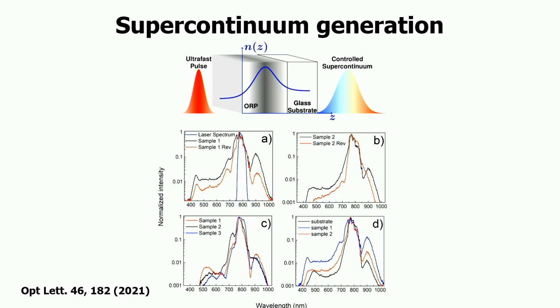So in these structures, we showed that we indeed have broadband negative GVD, and as a consequence, we can use them for enhancing the supercontinuum generation even from a glass substrate. So this optical reflectionless potential is on top of a glass substrate. Now, we coupled 5 femtosecond pulses to this and showed that we can enhance the UV blue region by up to 2 orders of magnitude in the efficiency of supercontinuum generation in these structures.